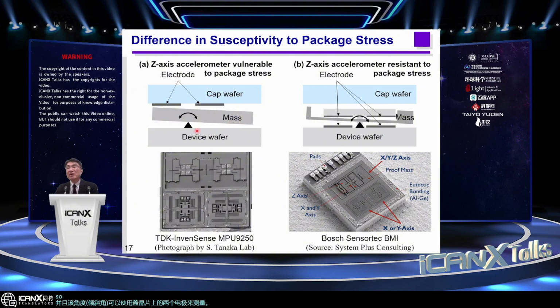But this is a very reasonable structure, easy to understand, but there's a problem. As I explained, there is a plastic on the cap wafer, black plastic that protects the sensors. And if the plastic deforms by temperature change or the humidity, the cap is pushed or pulled, and the gap between the electrode and mass slightly changes. That changes the sensitivity or the zero bias. So the sensor is not very stable in different conditions.